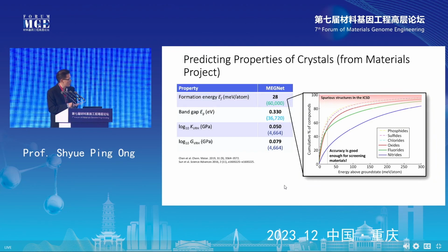So there's this work that was done a few years ago by Professor Wenhao Sun from the University of Michigan. And he showed that out of all the crystals in the ICSD, about 80 to 90% of those materials fall within 100 milli-electron volts per atom above the convex hull, right? And what this means is that once we get to an accuracy of about 28 milli-electron volts per atom or so, that is much lower than the limit for synthesizable materials, right?